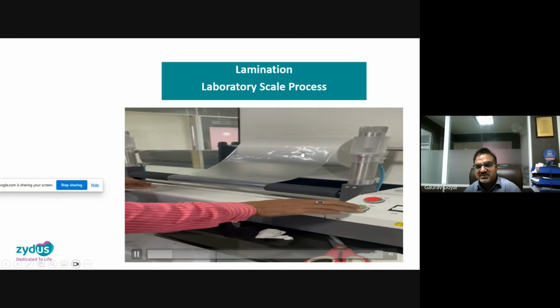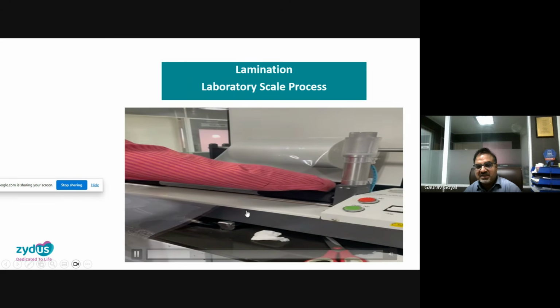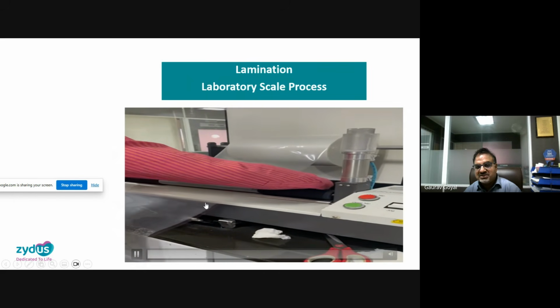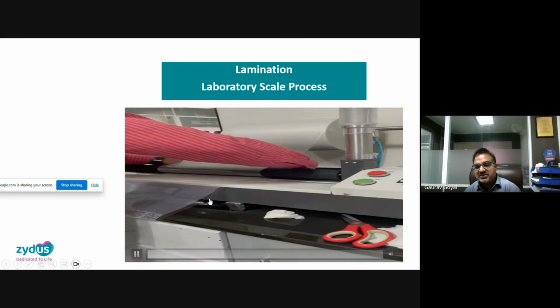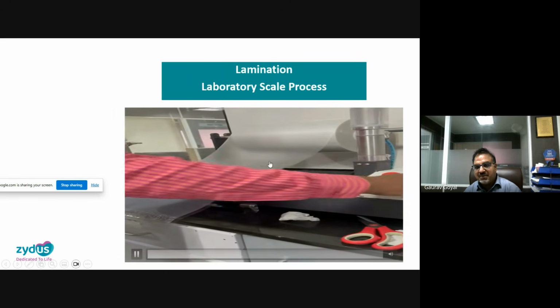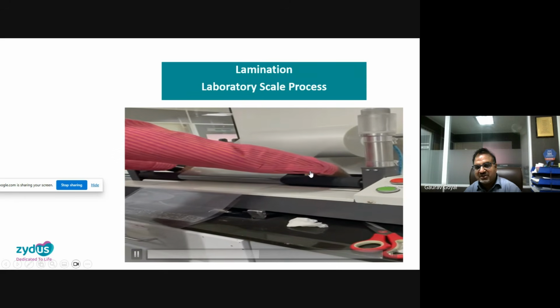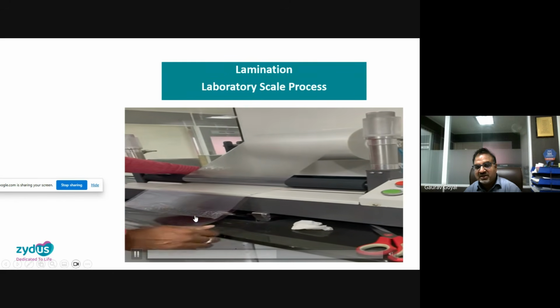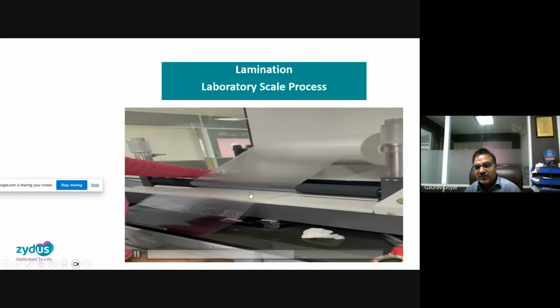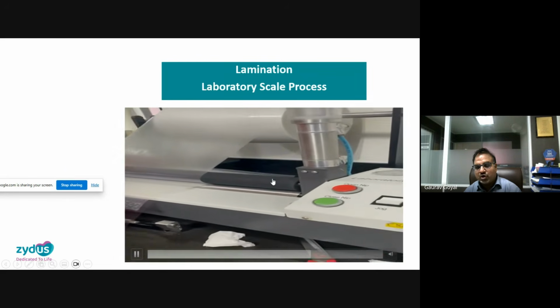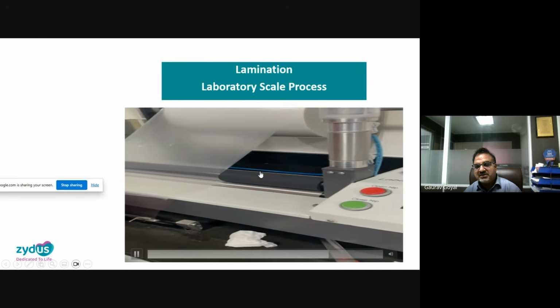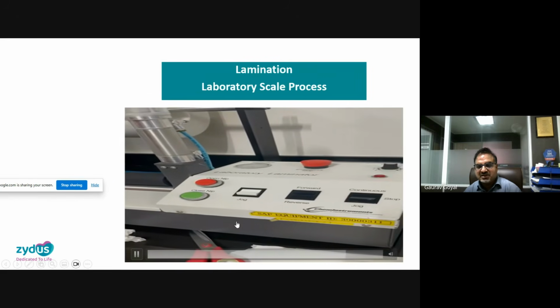So above there is a backing membrane. So this is the laminator. Below is the coated laminate which is there. From above, the backing membrane is sandwiched between the two layers. So you can see the below layer is moving from below and the upper layer is coming from top, and from behind the laminated patch comes.